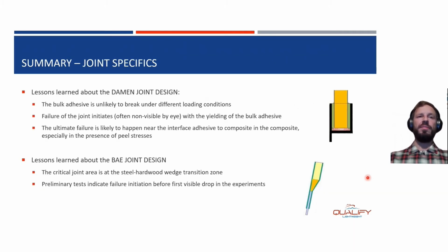Now, what did we learn about the joints? What we learned about the Dahmen joint design is that the bulk adhesive is very unlikely to break under different loading conditions. It didn't break at all. But the failure always initiated with the yielding of the bulk adhesive. So first the bulk started to yield, and then at some point we had failure of the interface here, of the composites here. And the ultimate failure is likely to happen near the interface adhesive to composite, so in this area, especially in the presence of high peel stresses.